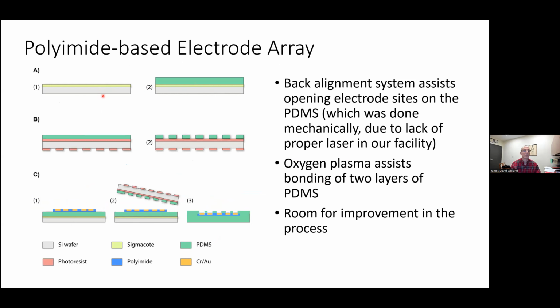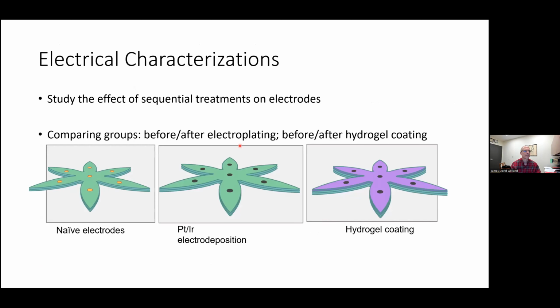This is a cross-section of the process where we've got PDMS. We make 2 different layers of PDMS, one which is solid, one with openings. And this was a non-optimal process. We actually had to mechanically go in and scrape out some of the PDMS. So these were fairly large features. We then transfer our polyimide array onto the solid layer of PDMS, and then sandwich and bond these 2 layers together. And when we get rid of the silicon wafer on the top and bottom, we're left with this device. We just pushed forward in spite of the deficiencies in some parts of our process in order to get the final device that we wanted, but there's certainly room for improvement.